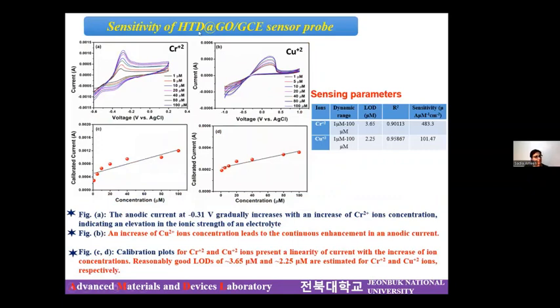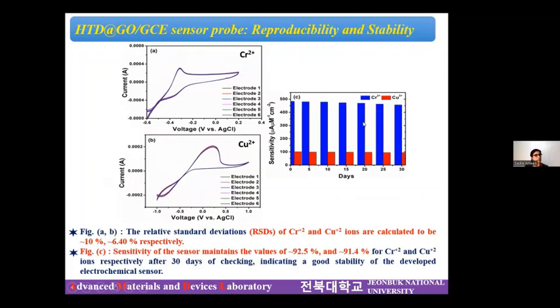And since our sensor is capable of detecting chromium and copper ions, we performed the sensing experiment, and these are the sensing parameters that we obtained. And finally, it is very important to know about the reproducibility as well as the stability of the material. For reproducibility, we made 6 different electrodes under the same environment, under the same room conditions, and we checked them for the detection of chromium and copper ions. All 6 electrodes showed almost the same performance. We did not see any major difference between them.